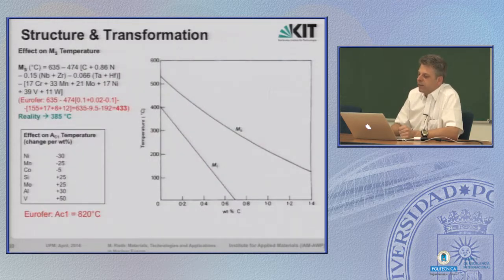And again, there are some empirical rules, more or less, for the metallurgical development of such steels. This is to influence the martensite start and end of martensite formation temperatures. Comparison of the rule ends up with a value of 433.